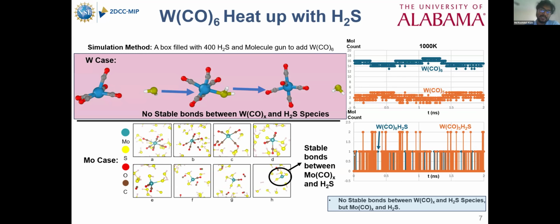But this case was not seen in the molybdenum case. In the molybdenum sulfur case, we have seen that there were actually stable bonds between molybdenum and sulfur. And eventually that also forms, at last, MoS2, MoS3, and also MoS4 species.